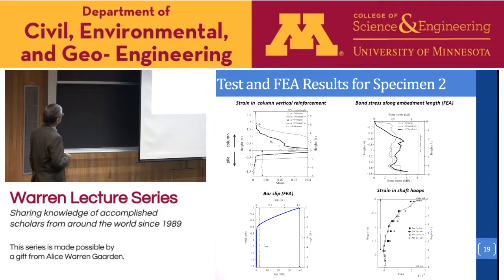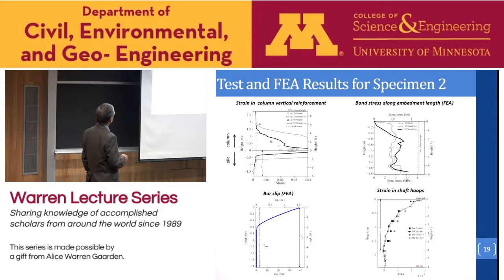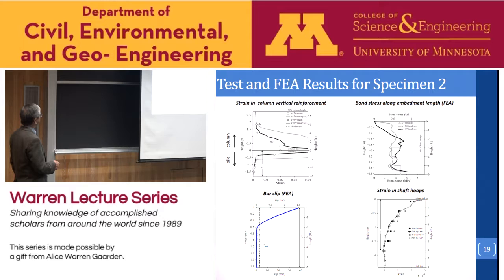So this shows more detailed comparisons between the test and the finite element analysis. This shows the strain in the column longitudinal reinforcement. Above zero is in the column, so this is the column reinforcement, and negative depth means it is the reinforcement embedded inside the shaft. Remember, this is the data obtained from cyclic loading. There are two ductility levels we compare: one is a ductility of 2, the other is 6.9. At ductility of 2, I think the comparison is very good. Then the data start to deviate at ductility 6.9, when the column was subject to quite a large number of cycles. But this is a cyclic test, so it's very difficult to match exactly. Beyond 6.9, all our strain gauges were damaged, so we had no data to compare.